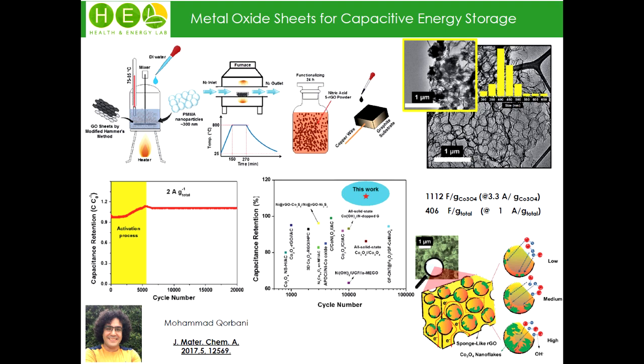It's probably related to diffusion of the electrolyte into the pores. We see that often in our experimental data, but not usually after 5,000 cycles—our activation is usually a few hundred, maybe 200 cycles. In which sweep rate do you mean? Because we had a very high scan rate here. Oh okay, yeah, when the scan rate is high, the number of cycles needed should go up. Correct, that makes sense.